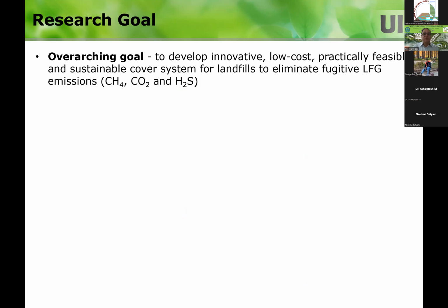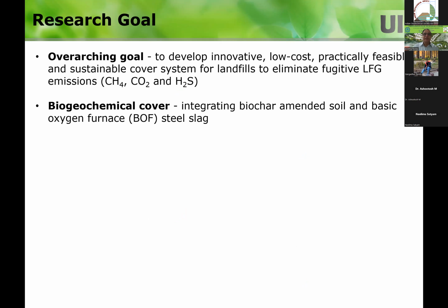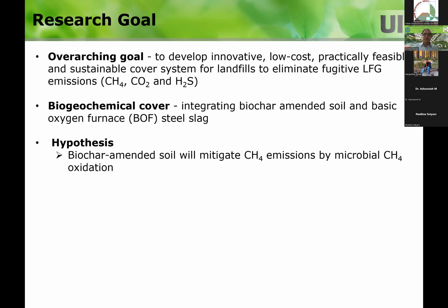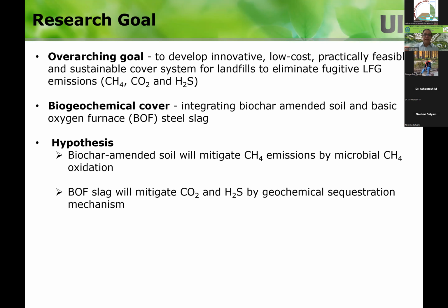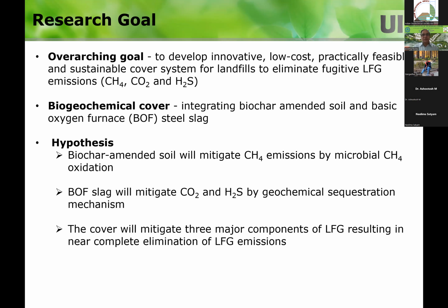Research goal was to develop an innovative, low-cost, practical, feasible, and sustainable cover system. Can we eliminate fugitive landfill gas emissions, especially methane, CO2, and H2S? So we call this one a biogeochemical cover. The hypothesis is that biochar amended soil will mitigate methane emissions by microbial methane oxidation, as we proved with our initial experiments. And then we want to add the BOF slag on top of it, so that the CO2 from the methane conversion, the additional CO2 coming from the waste, and the H2S coming from the waste, can we mitigate those using the slag? So basically, we are trying to eliminate these three gases that are coming out.